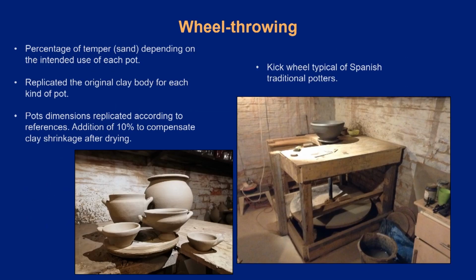The percentage of temper added to our local clay depends on the intended use of each pot. For example, for cooking wares, a greater amount of finely sieved sand has been added to let the clay body become more refractory during cooking. For each kind of pot, the original clay body, coarse or fine, and the dimensions have been replicated as much as possible, adding 10% in all dimensions to compensate for shrinkage. For throwing the pots, we used a kick wheel that was the most common among Spanish traditional potters until the introduction of electric motors in the 1960s.